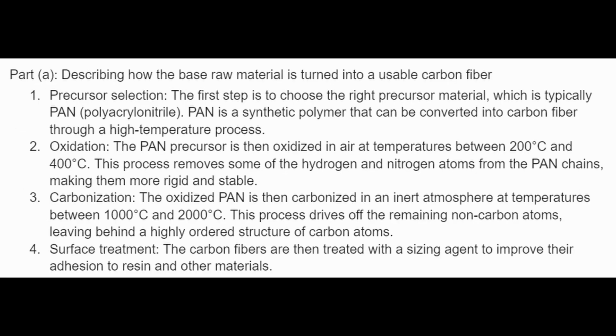A. Describing how the base raw material is turned into a usable carbon fiber. 1. Precursor selection. The first step is to choose the right precursor material, which is typically PAN, polyacrylonitrile. PAN is a synthetic polymer that can be converted into carbon fiber through a high temperature process. 2. Oxidation. The PAN precursor is then oxidized in air at temperatures between 200 and 400 Celsius. This process removes some of the hydrogen and nitrogen atoms from the PAN chains, making them more rigid and stable.